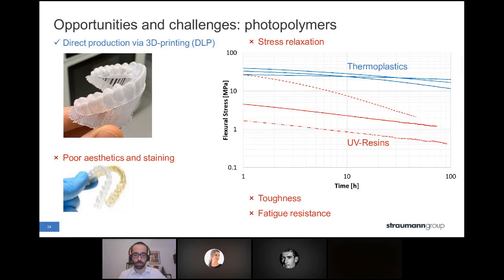And I wouldn't exclude that for the future, composites can be combined with photopolymers. And this might be the question that some of you have in mind: why aren't aligners directly produced via 3D printing? And the main answer is that the properties of most resins, especially methacrylate resins, are not good enough, both in terms of aesthetics, that they tend to have a not very nice finishing, and also are prone to staining, or also yellowish color. And stress relaxation, the ability to retain stress, is really poor for most UV resins compared to thermoplastics. Toughness and fatigue resistance are also quite an issue.